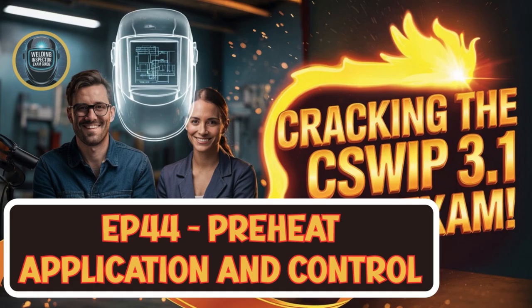Okay, lots of methods. So once the heat's applied, whichever way they do it, how do you actually know you've hit those very specific temperatures you mentioned? Where do you measure and when, especially if you've got a thick chunk of steel? Yeah, that's where the rigor really comes in. The measurement has to be taken immediately before the welding arc passes over that spot. Yeah, before the arc. Immediately before. And where you measure depends a lot on how thick the workpiece is. The source gives specific rules. For thinner stuff, say up to 50 millimeters thick, you measure within a certain distance of the weld, typically 4 times the thickness, up to a max of 50 millimeters away, and usually on the same side the welder's working on. Right. But for thicker sections, over 50 millimeters, you measure a bit further out, minimum 75 millimeters away.